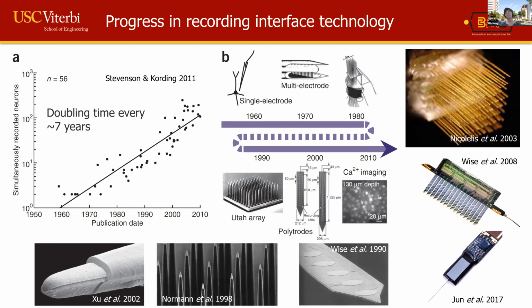In the early days, much of the recording was done using very simple, small diameter metallic microwires that are insulated all along the length of the wire, but de-insulated only at the tip. So you have a very small, well-defined region that can make an interface with the nervous tissue.